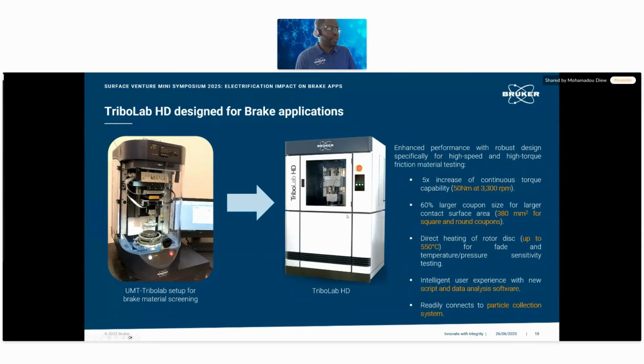This system has an embedded heating of the rotor disc. It means you can heat underneath the disc and get faster to 550. It will compensate if you do not reach the right temperature only by friction, increasing the temperature a little to get to the fading mode where the temperature can be higher. On this, you can add particle collection systems with an impactor and a pump that allow you to collect particles and do post-mortem analysis after the test, to get the size and distribution, and, with chemical analysis, information on the particle structure and chemistry.